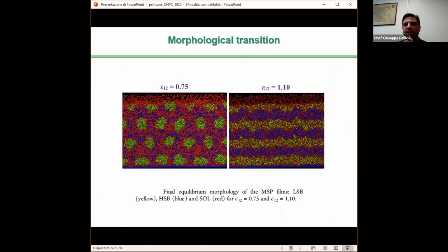If we look at this slide, classically, the morphology of block copolymers is controlled by the volume fraction of the various blocks. So in our study, we consider a symmetric block copolymer, and in absence of solvent, we expect it to form a lamellar type of morphology. So the solvent plays an important role and it virtually changes the volume fractions of the two blocks.